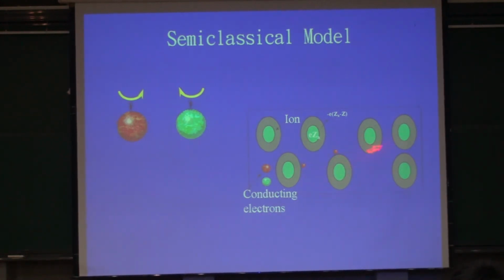And if they have spin-dependent scattering, the charge will not disappear during the scattering, but the spin will always flip over during the whole transport area. So if your transport region is much larger than the mean free path, then your spin on average flips more than 1 million times. So actually the spin property will be forgotten, but the charge is still maintained. So usually if you cannot go to a narrow size, you cannot use your spin collective effects in the transport phenomena, but you can use the charge. So actually the spin, even though they carry it, on average they forget it.